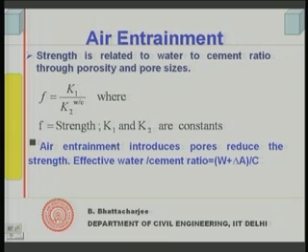And therefore, cracks might initiate from those places, but the air entrained pores will help, because the crack can propagate through them. One of the ways people try to relate this is, because we do not really have the compressive strength of concrete from fundamental concepts, relating it to the fundamental properties is still awaited. This relationship is an empirical relationship, and to use it, one of the ways is to use equivalent water cement ratio, W plus delta A, where delta A is the air content, and then use the W by C relationship.